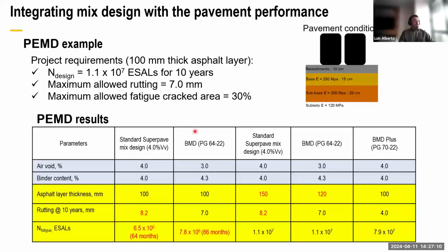When you optimize it by using the balanced mix design based on the pavement performance, we see that we could improve the material's performance. Look here, we kept the same pavement thickness. We could improve the rutting performance and also improve the fatigue performance. So it's a really powerful tool, because by optimizing the volumetric space, we could greatly improve the material performance, on the rutting side and the fatigue side at the same time. But the problem here is that even after optimization, we couldn't achieve the minimum fatigue life required by the project. So something that we can do is, okay, we have the rutting achieved, and in order to have the fatigue life attained, we can make the pavement thicker.